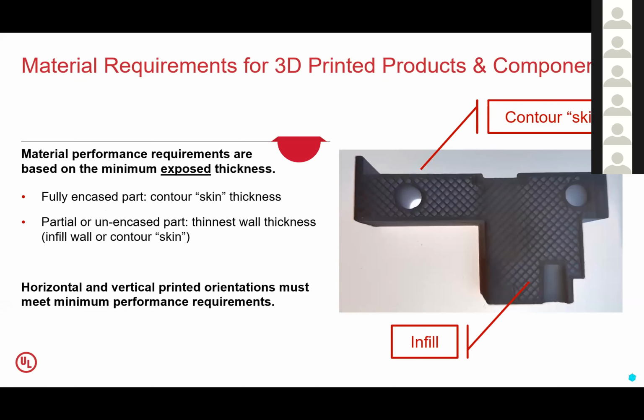An important aspect when we look at 3D printed parts is, how do we look at the part in terms of the thickness? So I show a cutaway diagram here of a 3D printed part where there's a lower density infill for weight savings purposes, and a thicker contour around the exterior and around some of the interior components. So what we want to consider is, what is the thinnest section that is exposed to the elements? And if that thinnest section is not compromised, then we don't worry what's behind it. So in this case, if we had our electrical components running through the holes or on the exterior, you can see there's a thicker contour. So we're only concerned that that contour is not breached, that contour has the performance required for that product. We don't worry about the infill, which may be thinner.